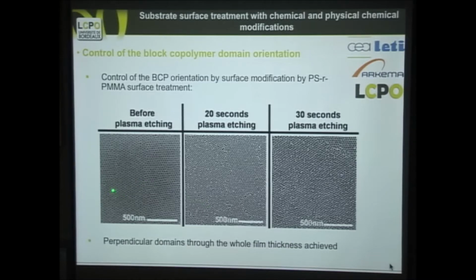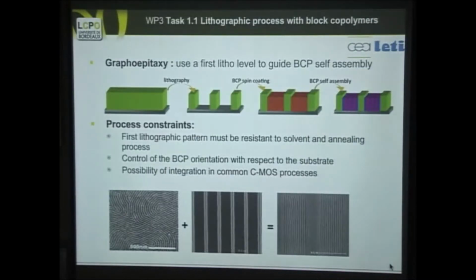By doing that, what we have found is that when we use the right composition, then we can see that the cylinders are perpendicular all over the thickness. When we make a thick film and then we etch it slowly, we find that they are going perpendicularly all the way down. But further on, how can we make them align in one direction altogether?